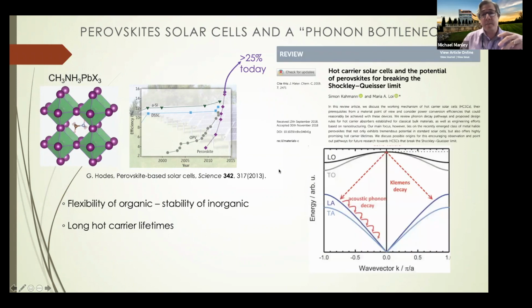And that is because of what we call a phonon bottleneck, or a hot phonon bottleneck. This is just a recent review article talking about this, that the electrons are unable to transfer their heat efficiently to the lattice vibration. So they transfer quickly to the optic phonon, but then there's this path where they have to exchange energy with an acoustic phonon, and then that has to spread out and decay.